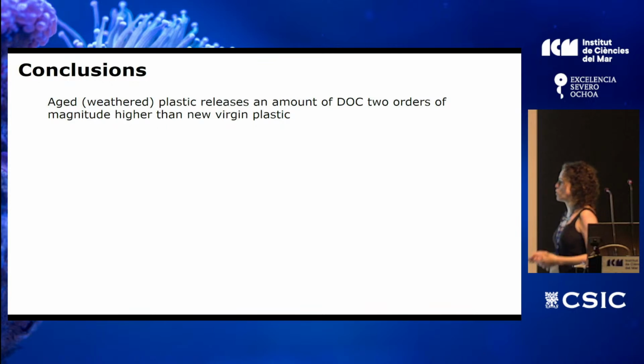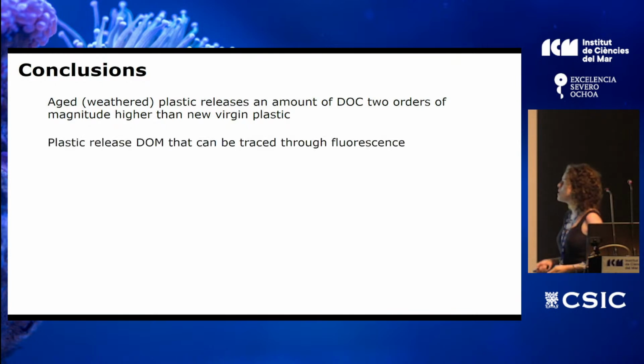So to conclude, from the results of all these studies, we know that aged or weathered plastic releases an amount of DOC that is 2 orders of magnitude higher than new virgin plastic. That plastic releases DOM that can be traced through fluorescence, and this is something that we want to explore now. I'm collaborating with Marco Talone because we want to see in situ if we can track the plastic through the fluorescence of the organic matter that is released.